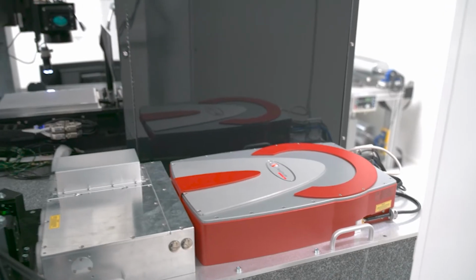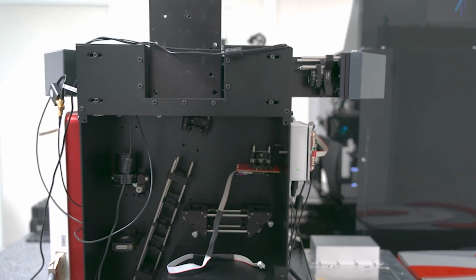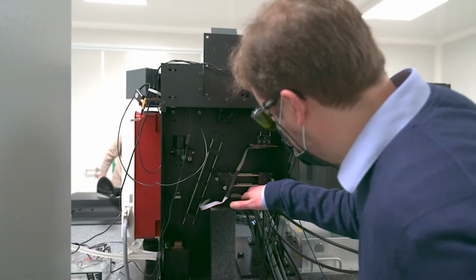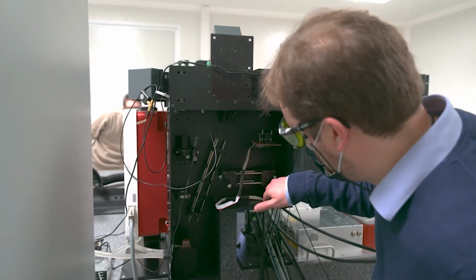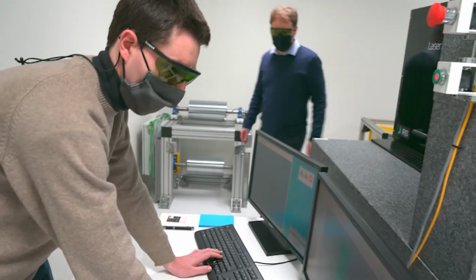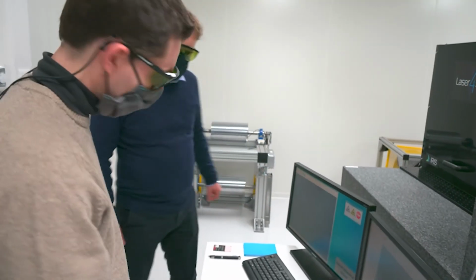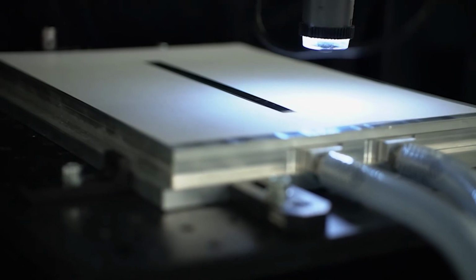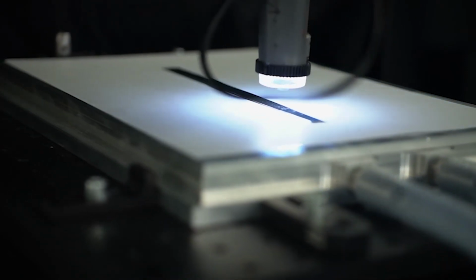With this new beam shaping module developed by Multitel, it is now possible to adjust the shape of the light from circular to square, the polarization orientation and even the pulse duration of the laser. This enables the engineers to create up to 1,200 lines per millimeter on the surface material, or more than 120,000 lines with one single laser scan.